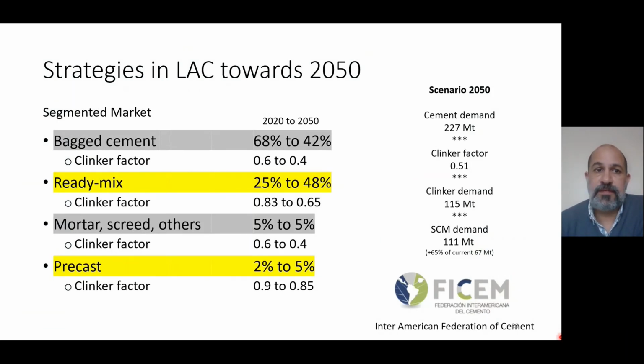So with this scenario, FICEM has built a strategy towards carbon neutrality in 2050, and this is very much relying on reducing clinker factor. But for achieving a more efficient reduction of clinker factors, the segmentation of the market seems necessary. So applications of cement in ready-mix concrete and precast, of course, will not allow such significant reductions in the clinker factor as applications in bag cement and mortar, screed and others that have no significant requirements as for performance, and in which the clinker factor may have reductions up to 0.4.